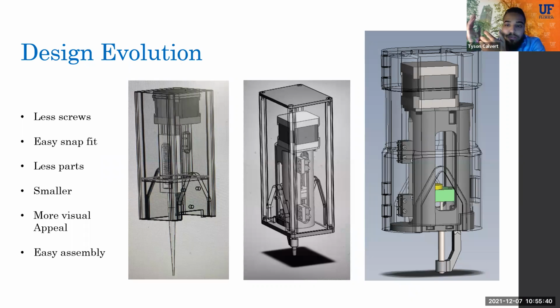Now, like all design projects, ours went through many stages of evolution. If one component was modified, the other components had to be modified to compensate for those following changes. Some of the major design changes include deciding to manufacture the chamber and plunger in stainless steel instead of 3D printing like we did for the rest of the design. As mentioned earlier, the purpose of this was to add a smooth finish, mitigating the possibility of air pockets occurring inside the chamber and avoiding leakage.